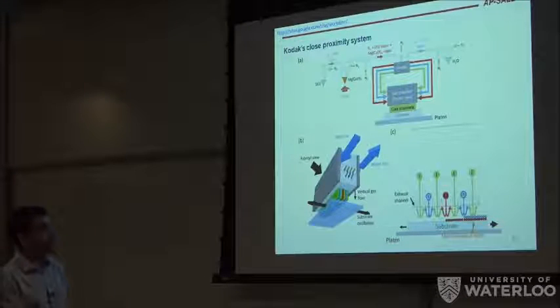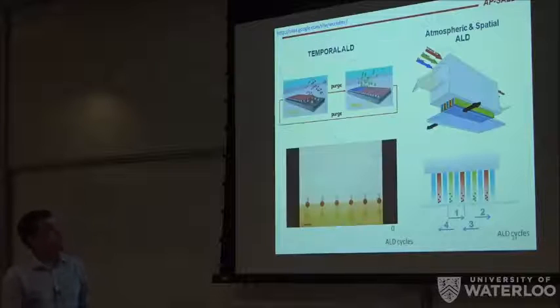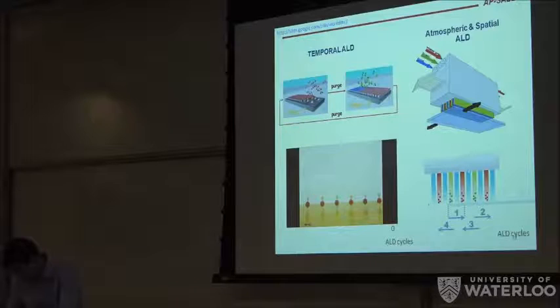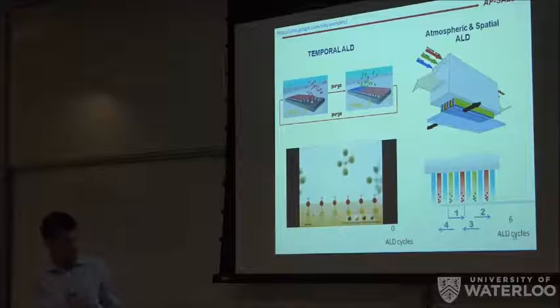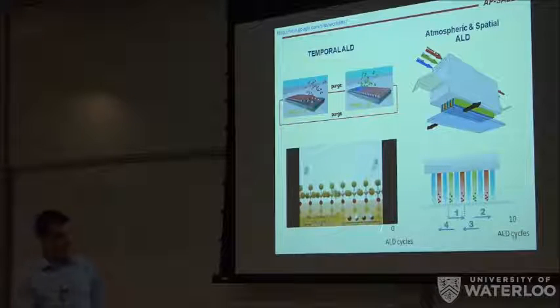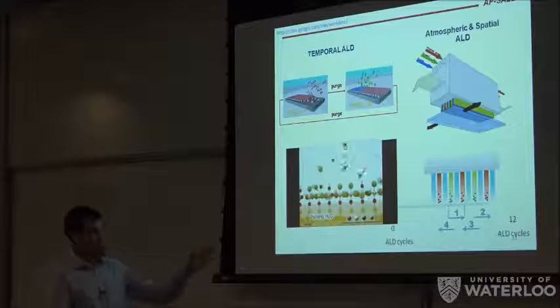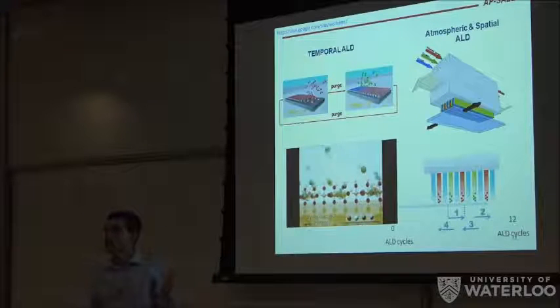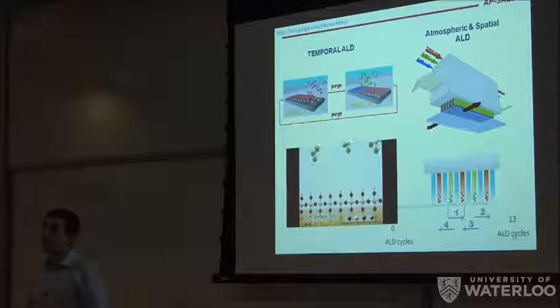So you can see that we can do it very easily. And here, for instance, is just to illustrate how much faster it can be. If we compare Spatial ALD, this approach, with conventional ALD, here we can see that every time we are scanning back and forth, we do 4 conventional ALD cycles. And by the time we've done 12 here, we are still at half cycle here. We just saturated the surface with a metal precursor. And of course, this is just an approximation, this is the order of magnitude of difference. Spatial ALD can be up to 2 orders of magnitude faster than conventional ALD. So it's quite interesting.